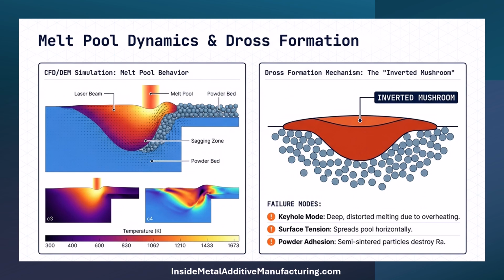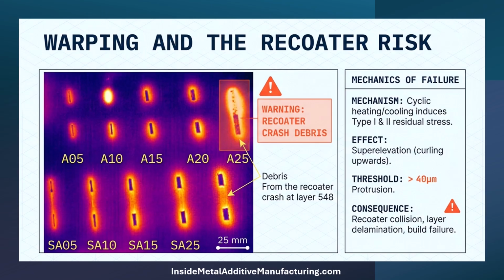In this state, the sagging zone extends deep into the powder bed. We see three primary failure modes here: keyhole mode melting due to excessive heat, surface tension spreading the pool horizontally, and powder adhesion, where semi-sintered particles ruin your surface roughness, Ra. Overheating isn't the only threat. The cyclic heating and cooling of these overhangs induce intense type 1 and 2 residual stresses. This leads to super elevation, where the part curls upward.